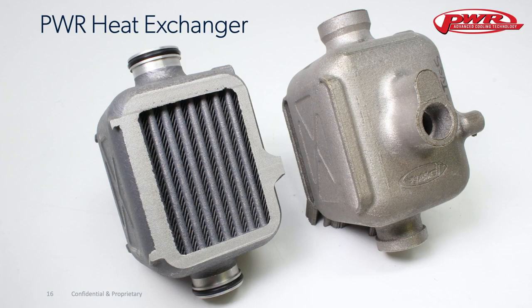What PWR did is they went around to all the major laser powder bed manufacturers and tasked them with trying to print both this very thin, difficult geometry, but also doing it with a high level of consistency of being leak-free, because obviously you can't have a mixture of fluids in an application like this. And because of our process control and our unique hardware, namely the recoater, we were able to print this part, print it well, print it consistently, and PWR decided to settle with VELO Sapphire as their solution.